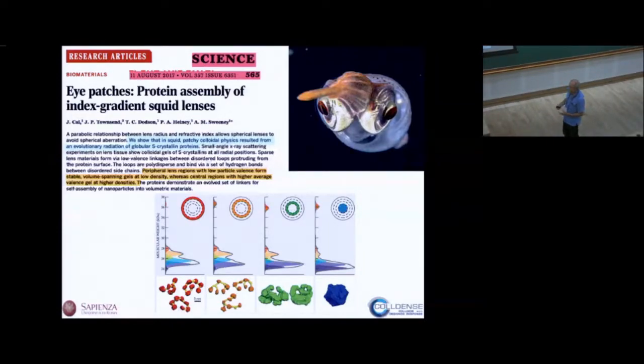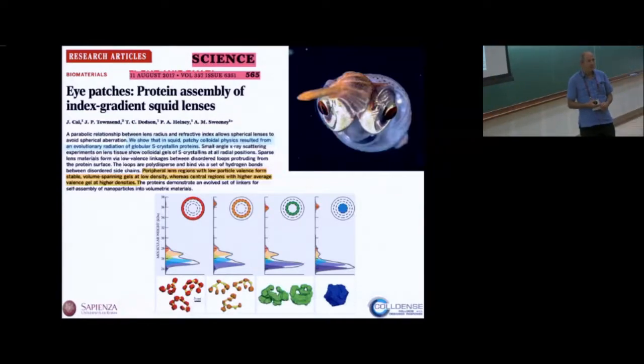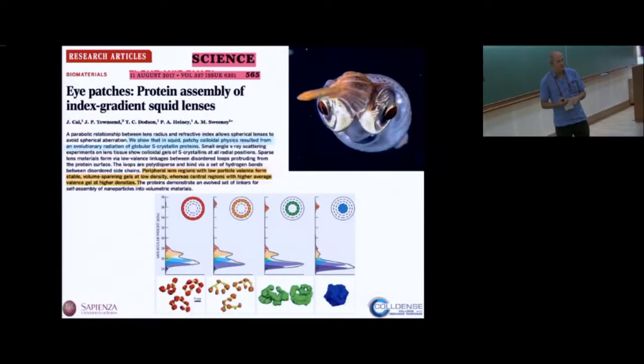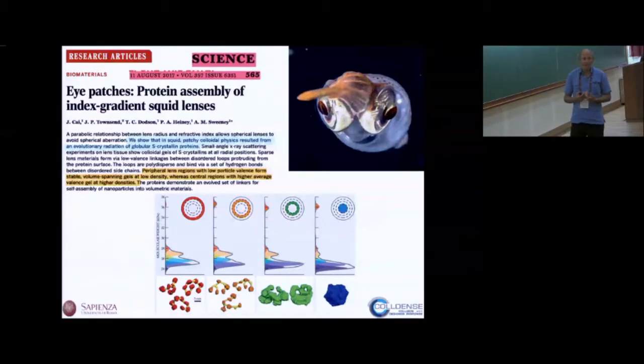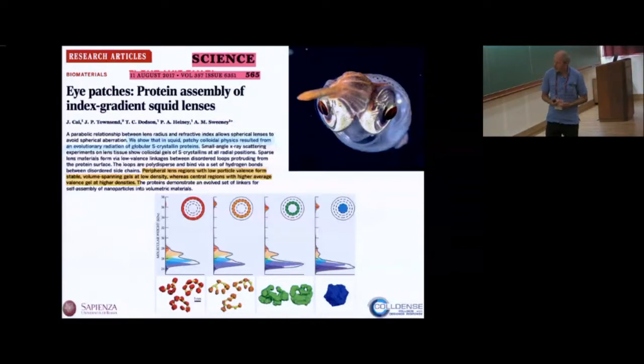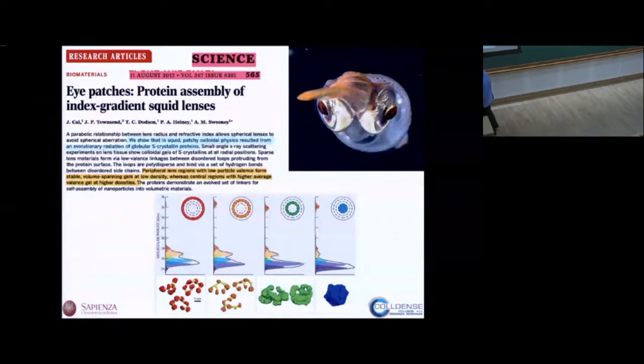And so you need to build a gradient in the refraction index in the lens of the squid if you want to correct for this aberration. Nature does it by generating gels of different density inside the squid. There are gels which are at very low densities. How can we do it? We can do it with proteins which are very directional.